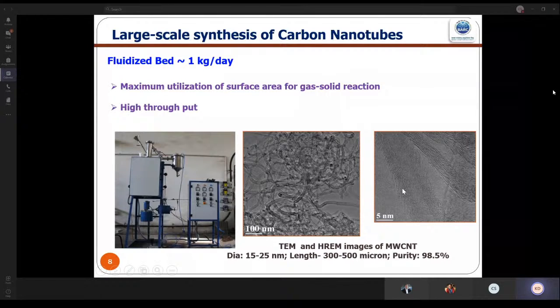We can go further with high resolution electron microscopy, where we can see the walls of the carbon and measure the number of walls. The wall-to-wall distance is typically 3.4 to 3.5 Angstrom. This is high resolution electron microscopy of carbon nanotube.